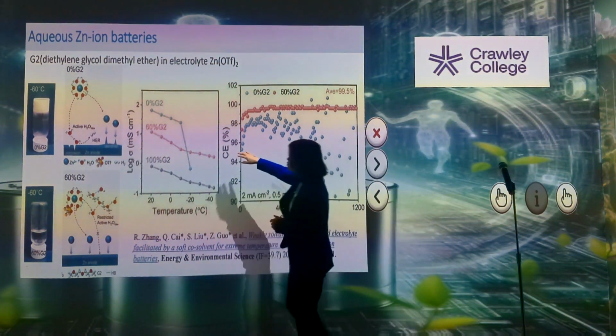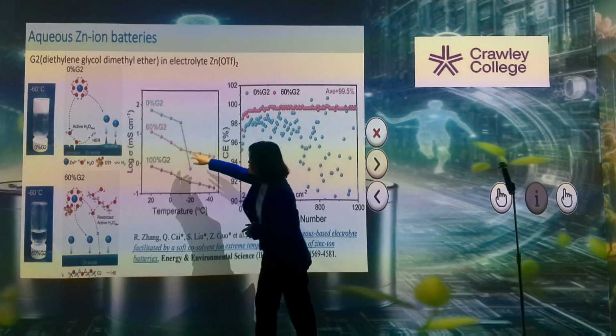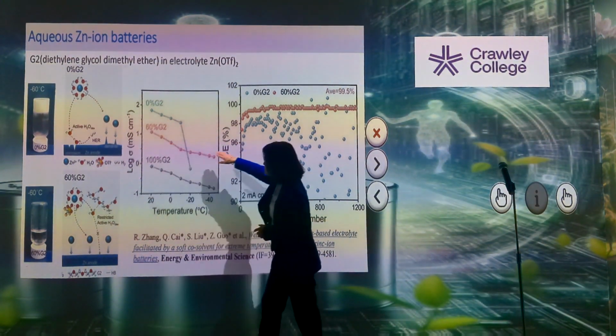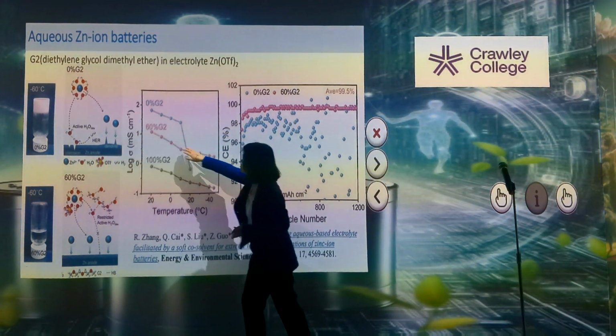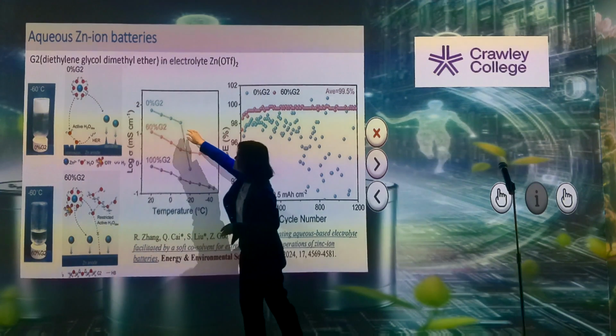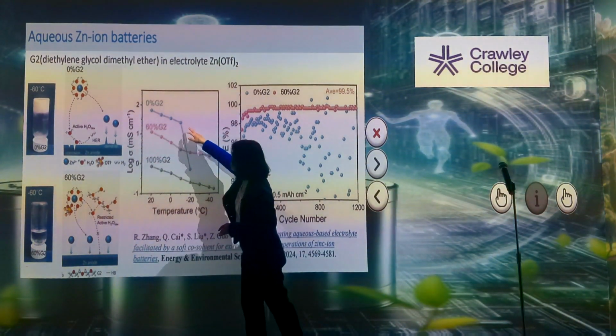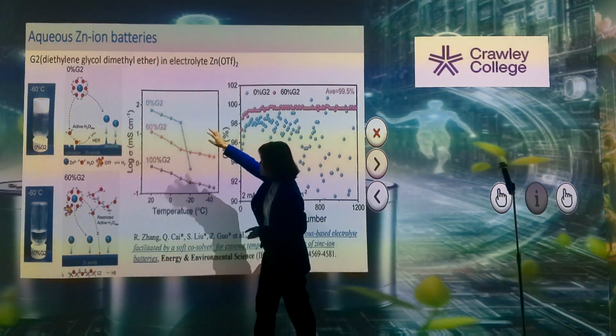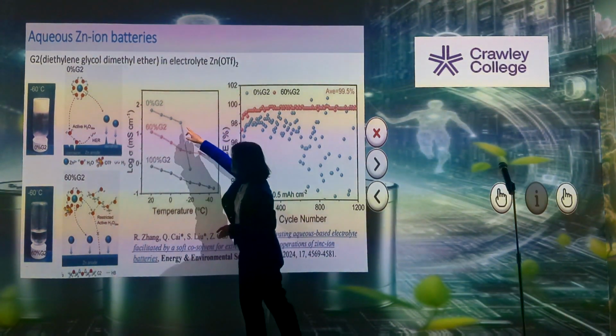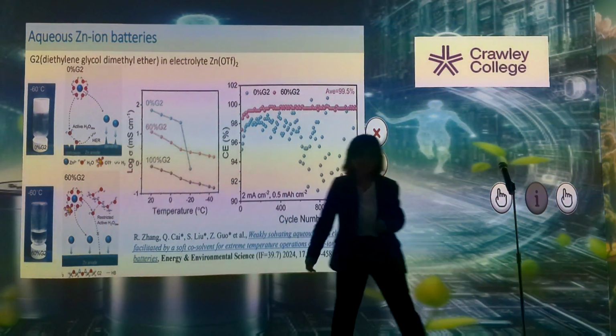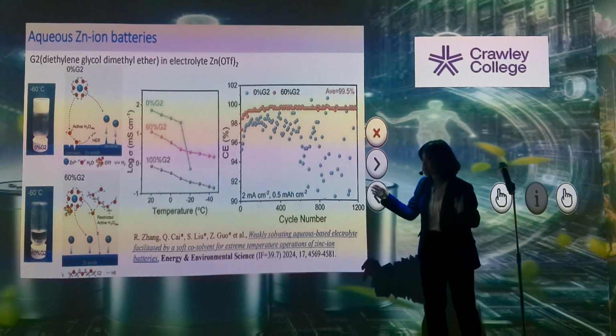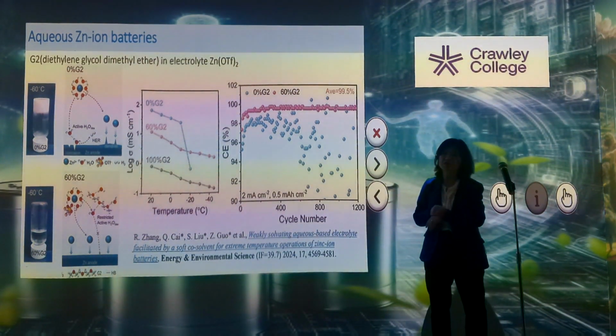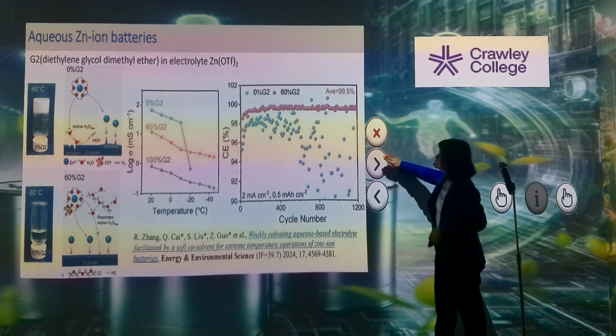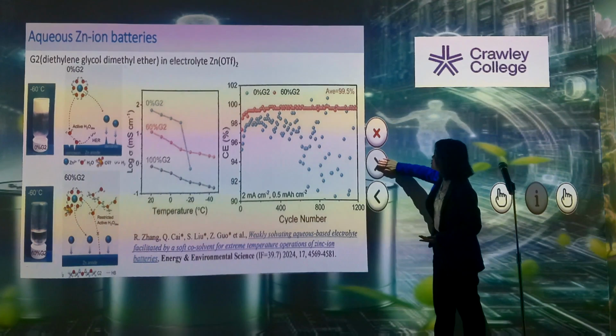And this is because the electrolyte with this 60% G2 molecule maintains relatively stable zinc-ion conduction mobility within the electrolyte, where the one without G2 molecules has a significant drop of the zinc-ion mobility once you reach temperature below 0 degrees C. It shows some promise for this type of batteries. And if we develop new materials, then we can improve the performance at both lower temperatures and also higher temperatures.